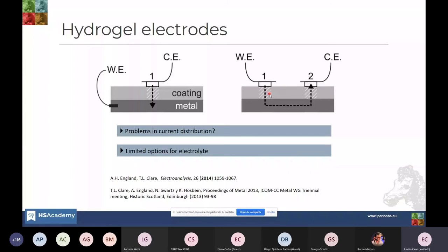The idea is that the current will flow this path through the coating, through the metal, and then again through the coating to reach the counter electrode. In this way you are actually measuring twice the coating, because the impedance of the metal is negligible, and you can just disregard that. The problem of this system, from my point of view, is there are, let's say, three main problems. One is that you cannot use a real reference electrode. You need to measure with two electrodes.